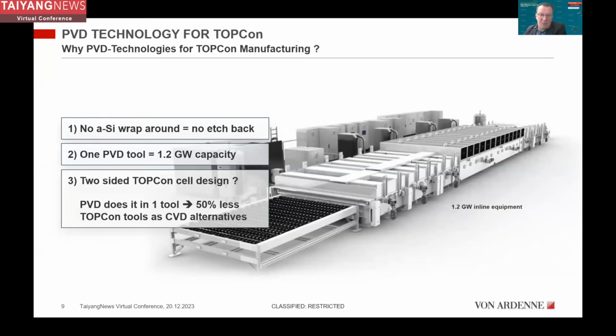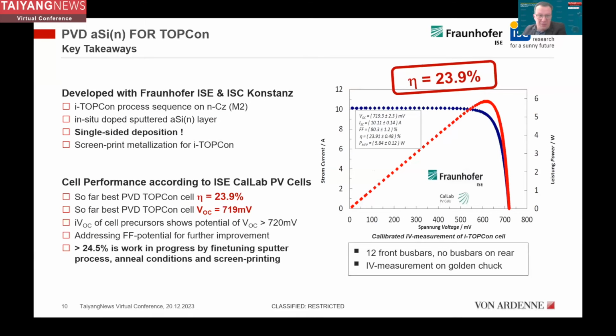And for sure, there's no limitation, or no really big limitation, when it comes to the size. So you see here a production equipment with up to 1.2 gigawatt in this case. And you can use this platform to do not only the rear side standard TOPCon coating, but maybe also the front side coating or the IBC coating. I come to this in a minute. But here, as a very straightforward TOPCon process, which is developed from Fraunhofer ISE and ISC Konstanz with a very standard rear TOPCon device, single-side deposition with front busbar design, we achieved an independently confirmed efficiency of 23.9% and a VOC of 719 millivolt.